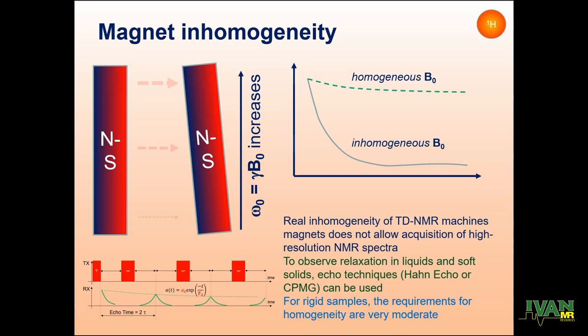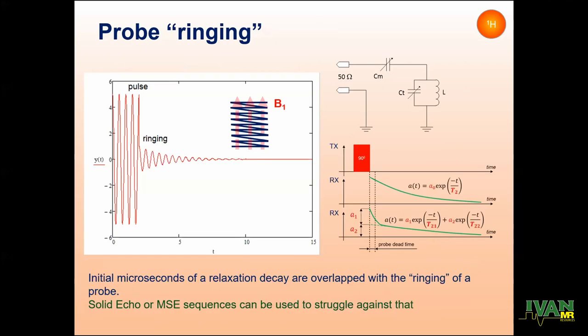For those reasons, the classical homogeneity of a time-domain NMR machine normally is more than enough to observe undistorted relaxation of rigid samples. Though to look at the relaxation of something with longer relaxation times, like liquids or soft materials, it's enough to use echo techniques to observe and measure relaxation times.